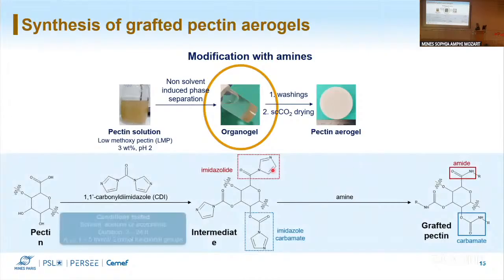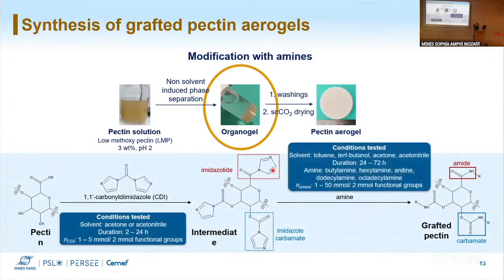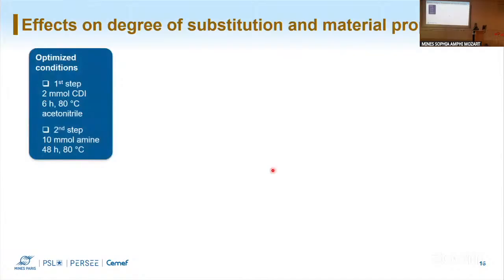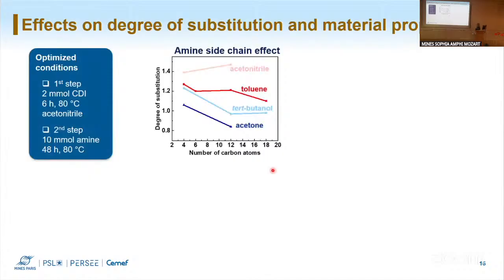We varied a lot of parameters for this reaction. So first we varied solvent, duration and amount of CDI. And for the second step, we varied again the solvent, the duration. We used 5 different amines and also the amount of amine that was used. So first we optimized the conditions. We did a lot of test experiments, and we used the conditions that are mentioned there for the further studies. And we can see here the effect of the size of the side chain of amine on the degree of substitution of our materials. And also we can see the different solvents, how they affect the degree of substitution.